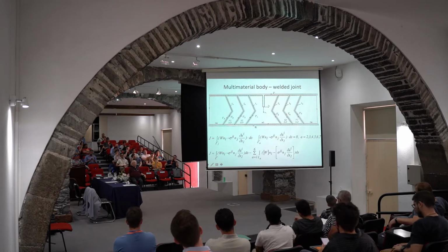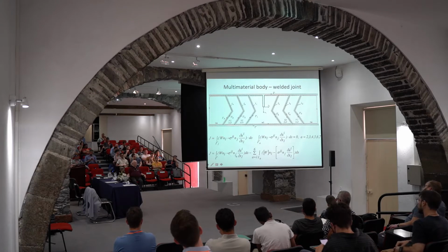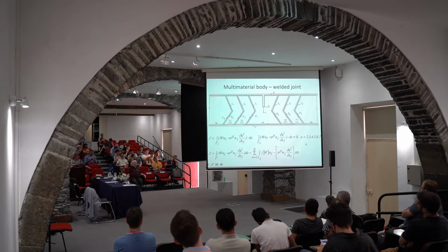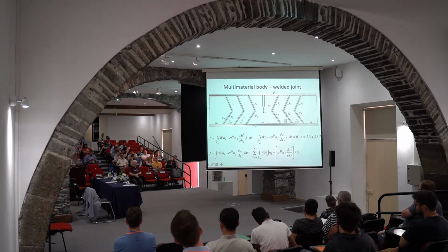Now we need to correlate them, and you can see that this J integral along the whole gamma path needs to be corrected with all these line integrals around these interfaces, and then it will get back its path independency property, and then it will be once again a valid fracture mechanics parameter.